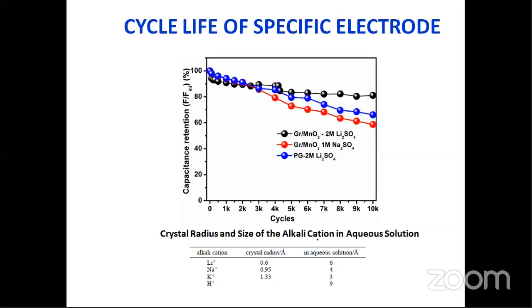So in this case, for example, if alkaline cations are used, lithium, sodium, potassium, or some H plus, in aqueous solution, the hydrated ion radius differs for lithium, sodium, potassium and H plus. That's why, for example, KOH is preferred in most cases, because the hydrated radius is very, very small, so that will give a better cycle life than any other system. This one I'm just giving for comparison purposes. If you vary the counter ions, how the cycle life performance of your electrode will vary. Okay, this is all about the cycle life.